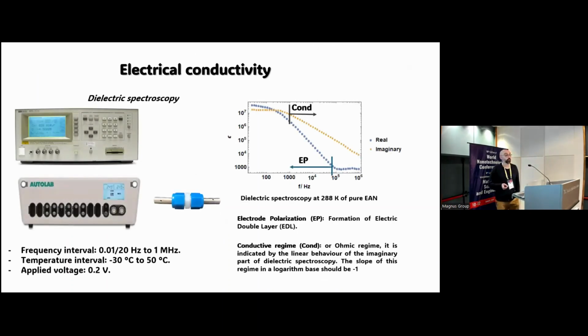We have also performed the electrical conductivity by dielectric spectroscopy with two different apparatus, from more or less 10 millihertz to 1 megahertz, on a temperature interval of minus 30 to 50 degrees at an applied voltage of 0.2 volts. You can see here the electrode polarization related with the formation of the electric double layer. That is the immediate layer at the electrode when we are applying a voltage. Okay, and the conductive regime that is going to be in our system. We're going to analyze this to see the imaginary part of the dielectric constant.